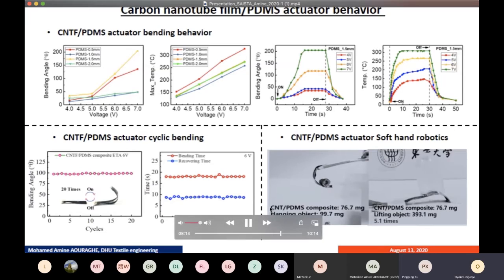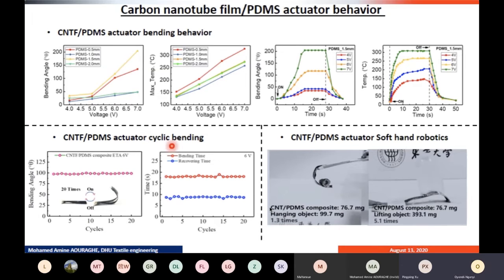In addition, the fabricated CNTF/PDMS actuators showed a stable response in time, with a stable bending angle of around 100 degrees at 6 volts, even after 20 cycles of on-off. And the bending time and recovery time also stay stable after 20 cycles. Finally, the actuator shows great strength and can hold around 1.3 times its weight and lift around 5 times its weight, as shown from these optical images.